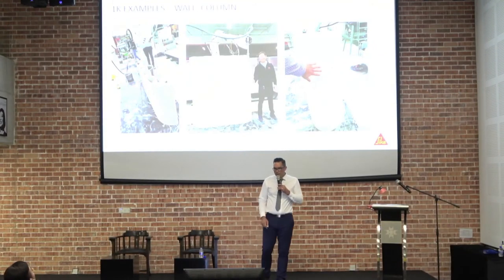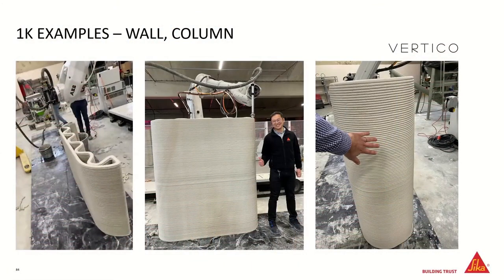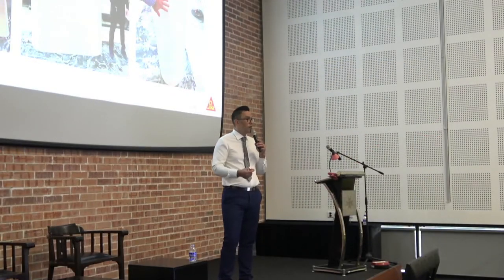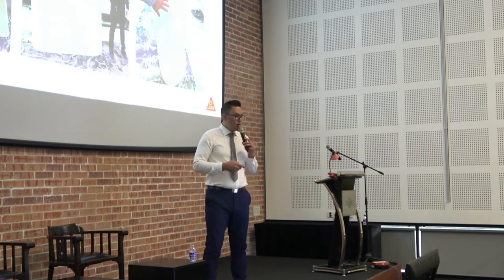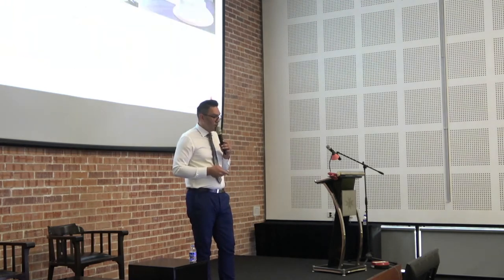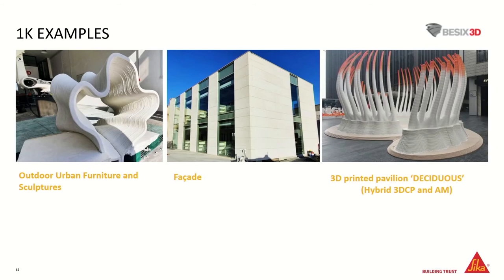Some examples, this kind of wall printed with a one component material, air cured, that took about, because it's slower, I think that took about an hour and a half. And then you can see that it's ready to go. The wall is finished. So you can see the benefits straight off the bat as far as time saving. It gives you a nice finish, and it gives you the freedom to design it. Other examples, we can do outdoor urban furniture and sculptures with the one component. You can print facade elements. Or you can even print hybrid. So the bottom half of that sculpture is concrete, and the top half is plastic, still 3D printed.